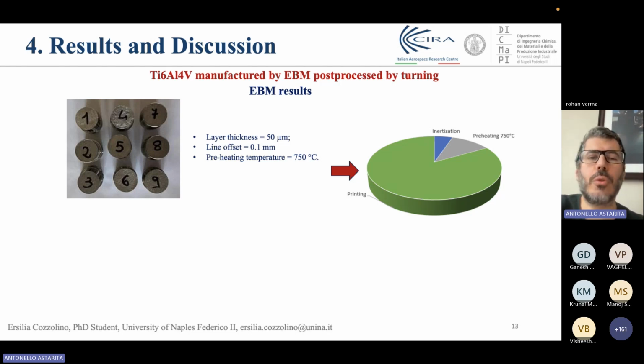In electron beam melting, you can have a higher layer thickness and higher productivity, but you need to keep the building chamber under vacuum, and usually the vacuum is much more expensive than the gas, of course, and you need to keep the whole printer job at a preheating temperature for titanium of more than 700 degrees. This is also very important because in calculating the sustainability of the process, you will see that this preheating temperature has a not negligible effect.